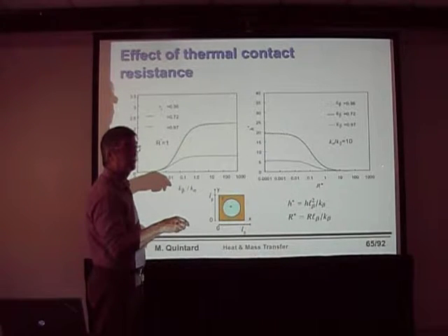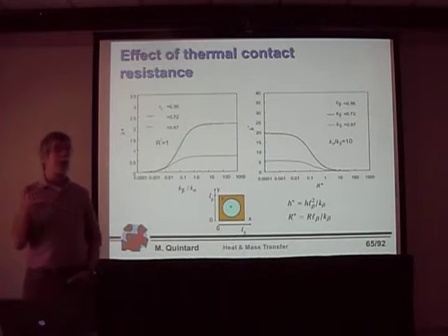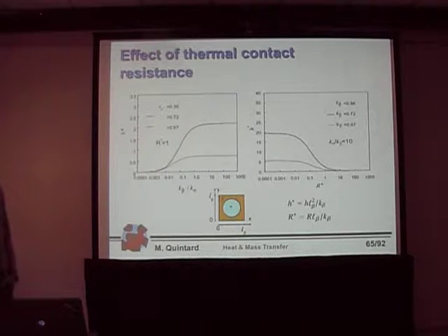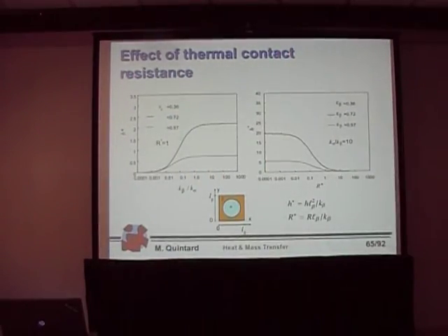This is something we expect. And in that case, we almost all the time will have non-equilibrium. And this might be very important for the application I worked on for this particular problem, which was the heat transfer in composite material. If you have delaminated composite, for instance, because of some mechanical stress on the system, or some manufacturing process defect, then R will increase, and the thermal behavior of your composite material will become very, very bad.